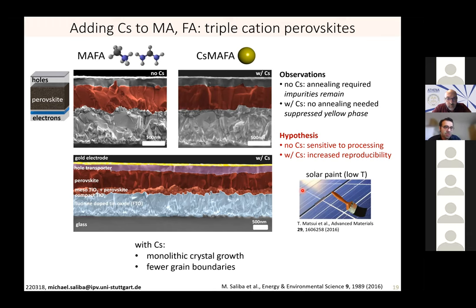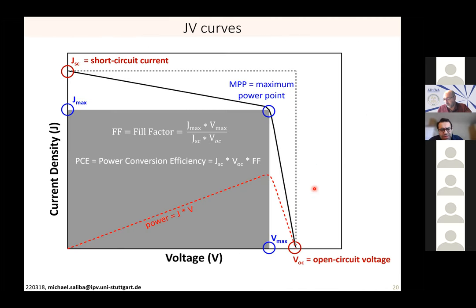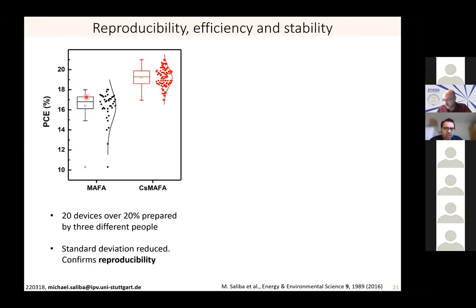And this is just a side result, but by adding larger amounts of cesium, because this already forms at room temperature, it gives rise to the idea of a solar paint, where the correct phase is formed from the very beginning. So I think for this audience, I can skip over this slide. These are the device parameters, measuring the efficiency of a solar cell. To cut the story short, by adding a small amount of cesium for these triple cation perovskites, a lot of the devices started to break the 20% threshold at the time. And very importantly, the standard deviation went down as well. You see it here, it was very mixed.